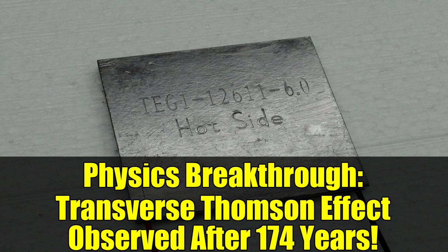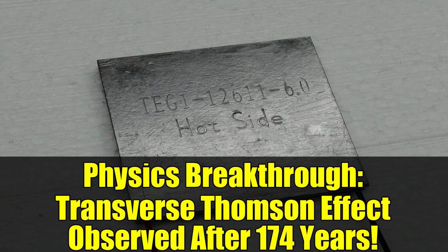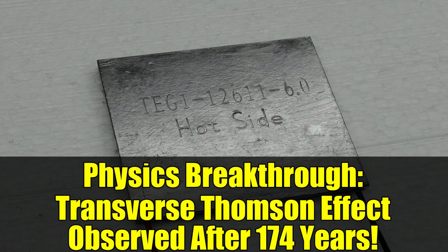Surprising results and future directions. To their astonishment, the researchers discovered that they could switch between heating and cooling simply by changing the direction of the magnetic field. This finding has the potential to enhance the efficiency of transverse thermoelectric cooling devices significantly. Looking ahead, the researchers are committed to exploring materials that are most conducive to producing the transverse Thomson effect. They believe this area of study will be a vital focus for future research.